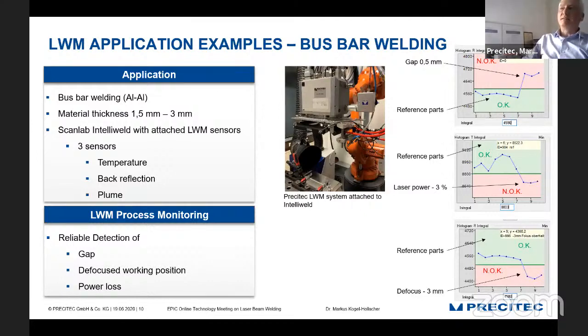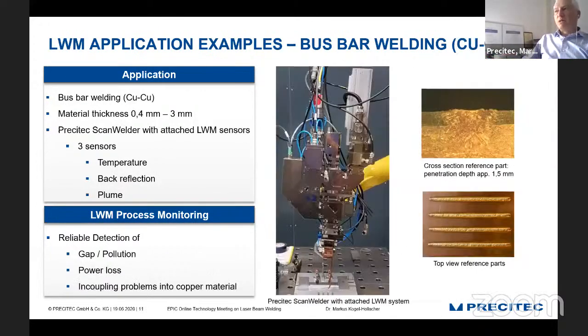And you see that different sensors, in that case temperature and back reflection sensors, can catch these errors very dominantly, and can distinguish good from bad parts. Another application in busbar welding, when it comes to copper welding, you see one of the processing heads of Precitec here in combination with sensor technology. This is what we call scan welder. It's a 1D scanner. It will occur later on in a different application as well, but in case we can use our own processing heads, it's quite easy to adapt our own sensors, and it's quite easy to select the right mirrors, the right glasses.